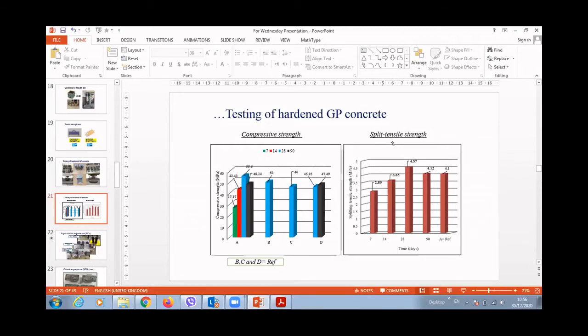The splitting tensile strength is on the right side. Because there is a linear relationship between the compressive strength and splitting strength, it increased with time and decreased also after the 90 days with a very slight decrease. But both of them give us very good results compared to the OPC.